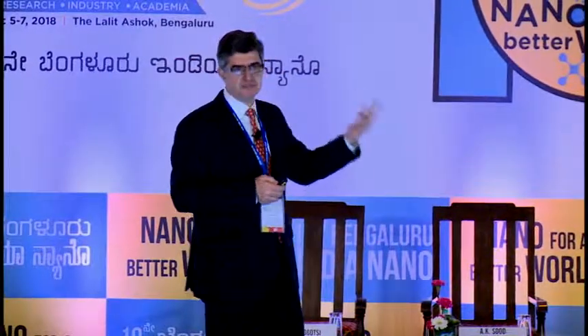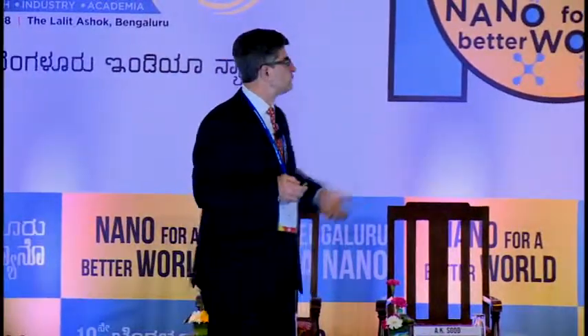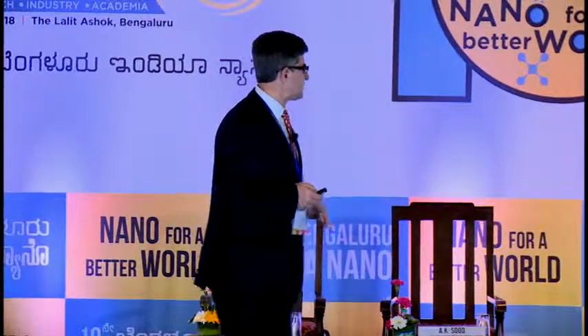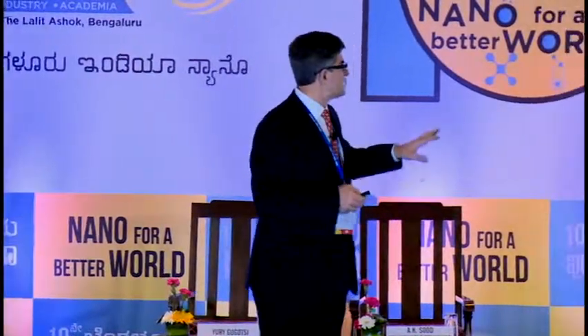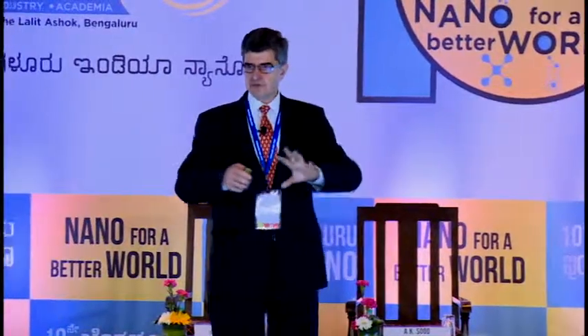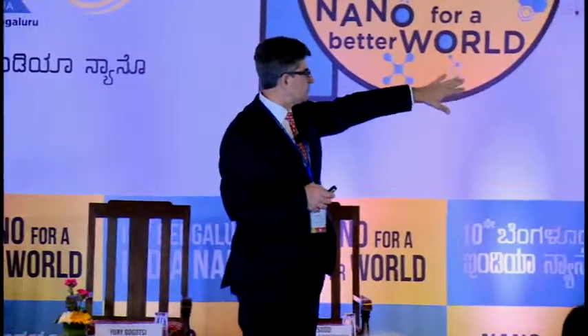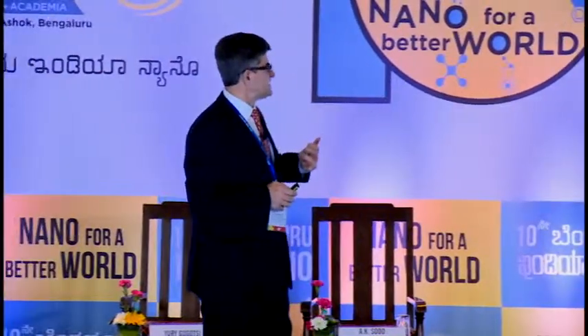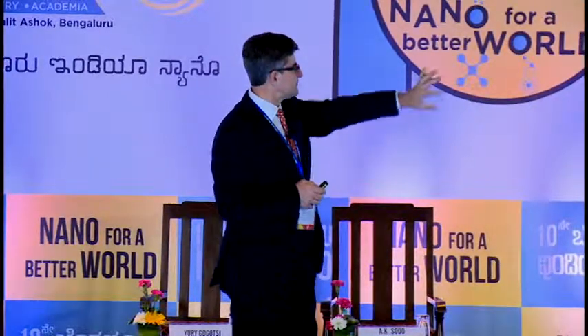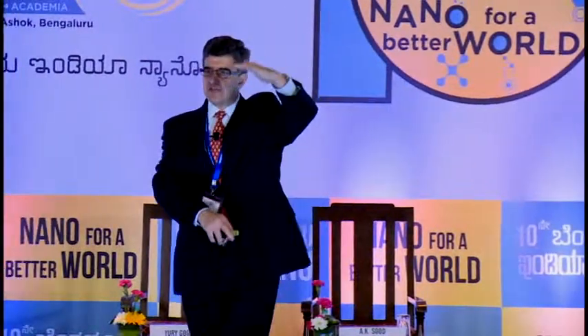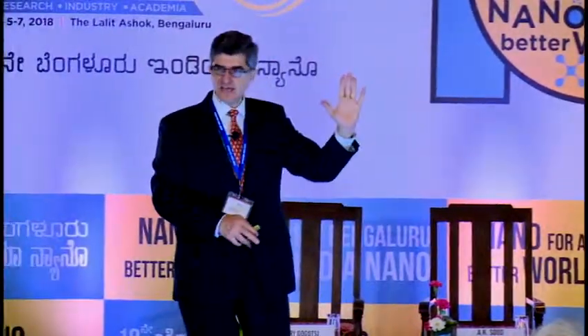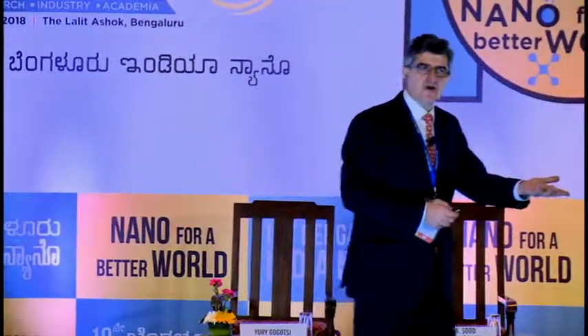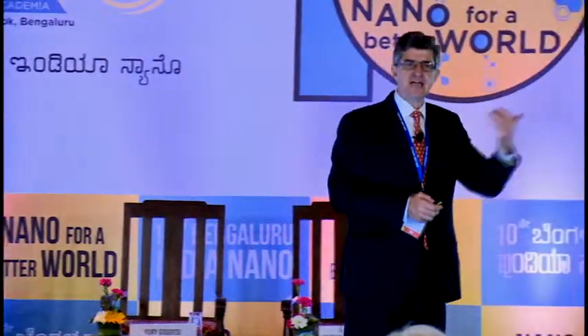So what we do, we started to build devices, looking into the mechanism. What can be done with this? This work was published last summer in Nature Energy, showing very interesting behavior. People who work in the electrochemistry field can recognize there is a capacitive envelope close to 0 volt. This is actually in acidic electrolyte, a titanium carbide Ti3C2 MXene film. But there is just a very large peak, which is actually reversible. We call it electrochemically reversible because there is no difference in the potential between the charging and discharging curves. So it charges like a supercapacitor, very, very quickly and at the same potential.